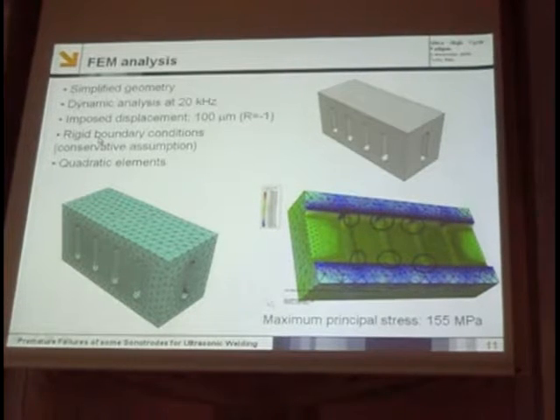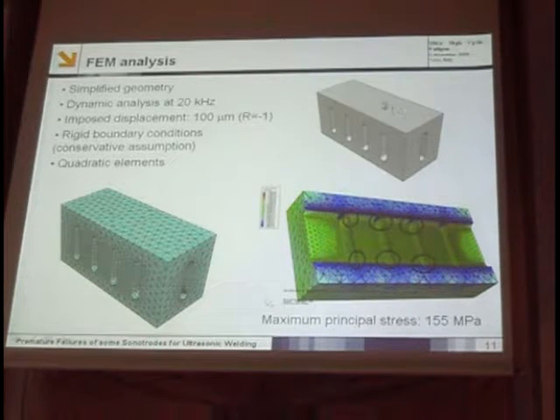We made quite a strong assumption, I think, because the sonotrode is the last of a chain of elastic elements, while we consider only the last one, and we rigidly bound it on one of the surfaces up here. So perhaps this assumption is quite conservative, because it is possible that the maximum principal stress that we found is higher than the real one for all the real elastic chain.